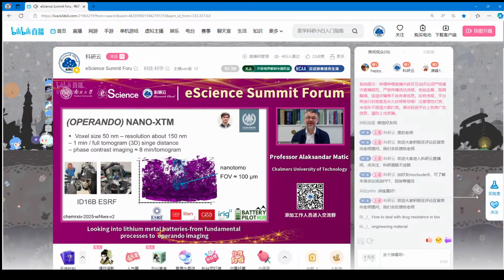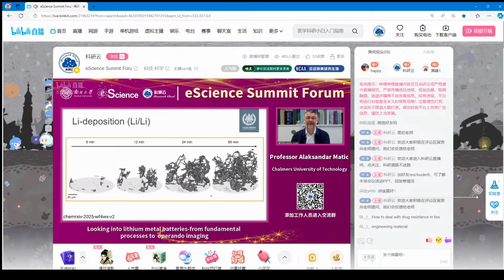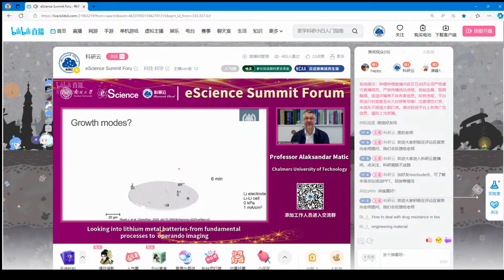But still, we can now follow, and here we follow the deposition at 6, 12, 24, and 60 minutes. And this paper is under review, so it's available on arXiv. But now you can see that we can, in much more detail, actually resolve the structures here in the deposited lithium. And we can start to understand growth mode. So if we look here, for instance, at 6 minutes, we're just depositing lithium in a few places on the electrodes. And it's from these places that you then start to grow, and the growth continues further and further into 60 minutes. And it's really preferential growth from these structures.